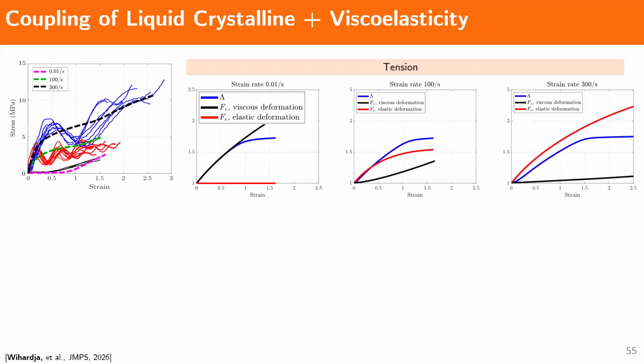Okay, so here are the results. These multiple curves are the experimental results, and the dotted lines are the simulation results. The experimental data is slightly noisy, but what we can see here is that this is under low strain rate, and you get stiffening as you go to higher and higher strain rate. So this makes sense. You get this stiffening at the highest strain rates in these materials.